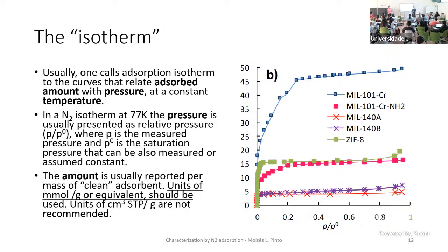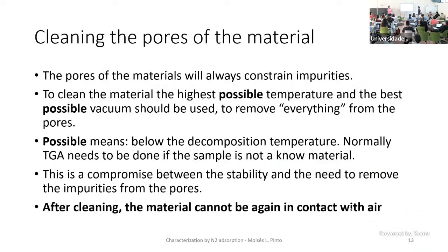You should try to avoid it, in my perspective, and also according to IUPAC recommendations. It's not just me. Why? Because this can mislead you. You can look into this as a volume, and in fact this is not a volume. Cubic centimeter STP, standard temperature and pressure, is an amount. So the values in here, if they are in STP, can mislead you to think that you have volume like this inside the pores, and you don't have it. We are going to calculate the volume of the pores in a different way, as we are going to see. So, cleaning the pores, just for you to understand what you need to do.